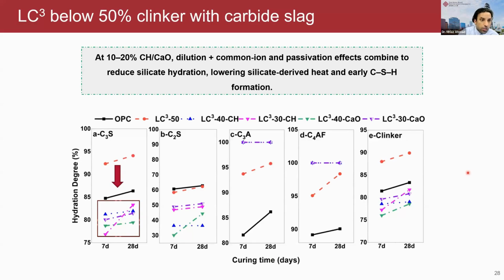However, everything is not perfect. If you can see that here at this high replacement level, there's a large amount of calcium coming from this calcium hydroxide. It significantly retarded the hydration of the clinker, or hydration of the cement. You can see that in the properties of this 20 or 30% cement we have in the system. But it also gives us some clue about what is happening. It means if we are able to further improve the reaction of tricalcium silicate and dicalcium silicate, we can further increase the performance of the LC cube 30 and LC cube 40 systems.